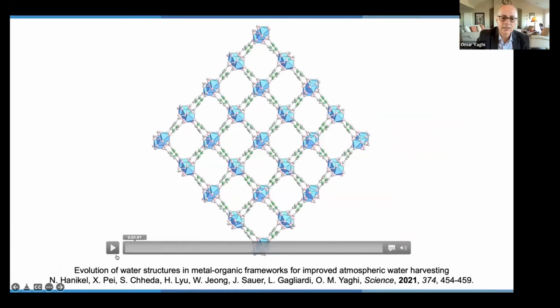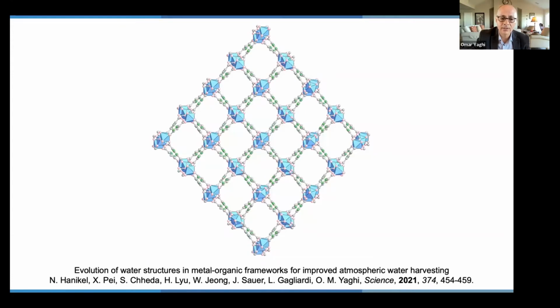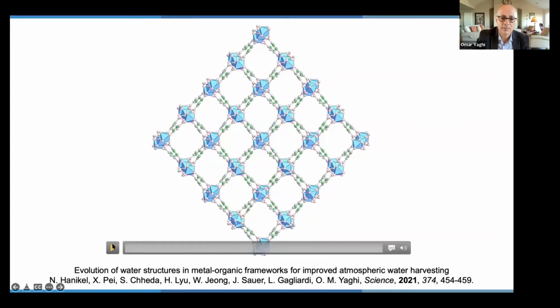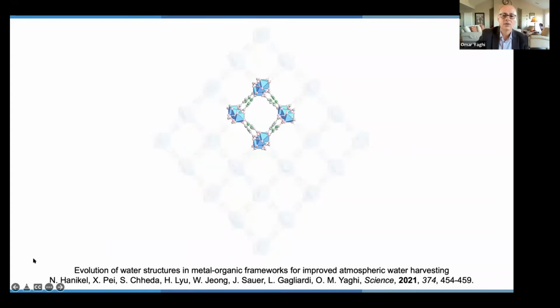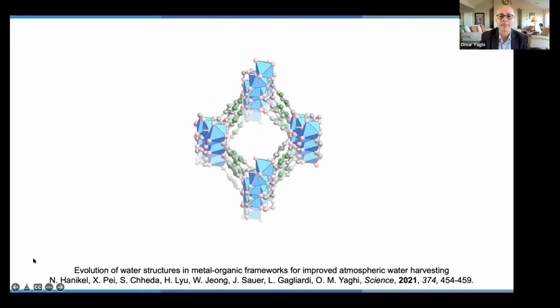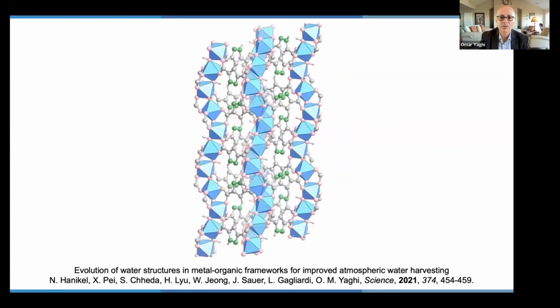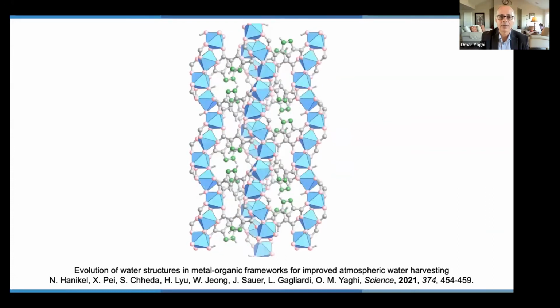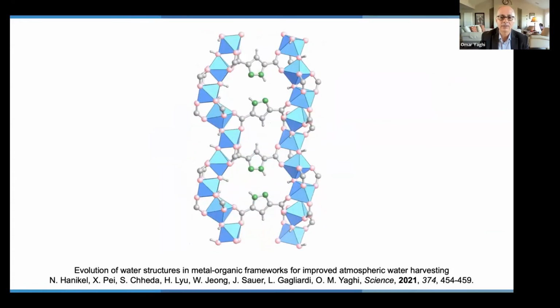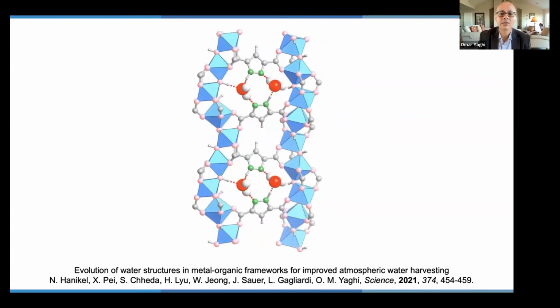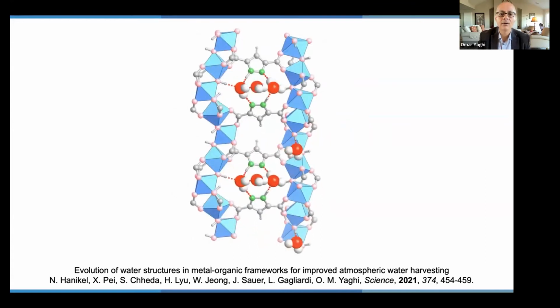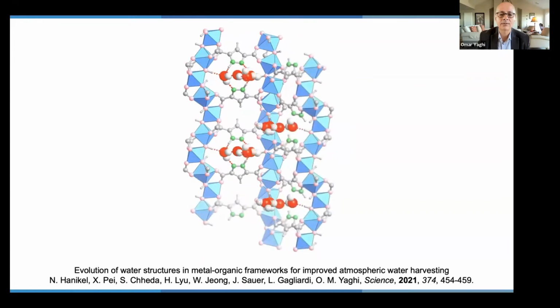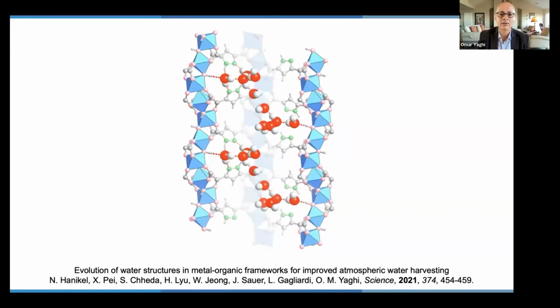So using X-ray diffraction, we have figured out the position of each one of the water molecules in MOF-303. And this is a movie that will show one pore. We're going to cleave the pore in half to show where the water molecules are going. They first enter into the hydrophilic regions. That's it. And now you start building up the structure of water in the hydrophobic regions.